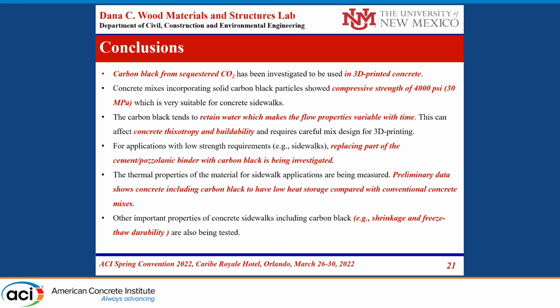For applications with low strength, as I said, replacing part of the cement is the next step. We believe that because the carbon black we are using is a highly fine material, if we replace the cement, that would also help us with the water management in the mix. That means replacing cement and pozzolans with carbon black rather than replacing the aggregates.